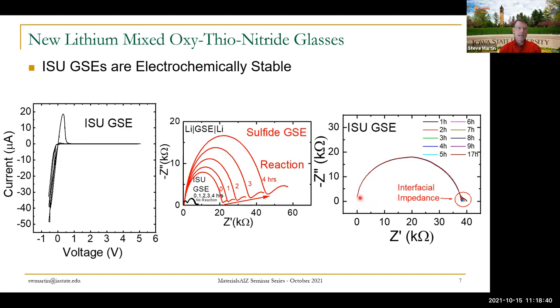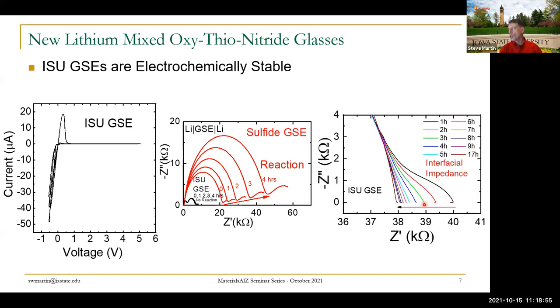And then you can see, again, this is for the battery geeks out there, there's a simple arc that shows the bulk impedance. And then there's a little bit of interfacial impedance, which at 17 hours, if I flip to the next slide, actually goes away. There's some kind of small interface there initially, and then that interface goes away, meaning that the interface is no longer present and not limiting our conductivity, which is of course exactly what we want. So we have demonstrated these glasses can be tailored through their wide compositional ranges, with significant benefits of all these properties. So let's look a little bit more in detail now at some specific compositions that we've been working on more recently and some of the optimized processing techniques that our group has developed.